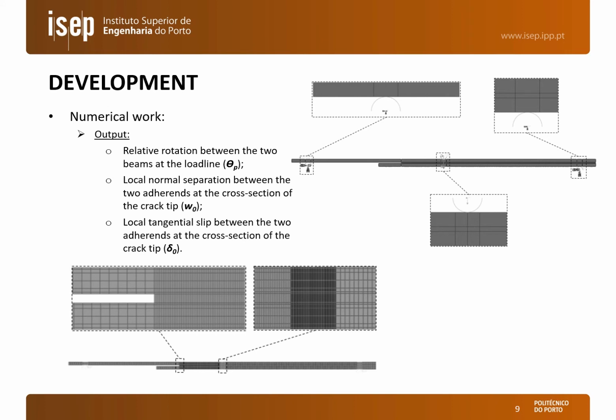Regarding the numerical work, we performed numerical models of the SLB tests such that we could extract 3 relevant parameters to obtain the G1 and G2 and also the cohesive laws in tension and shear, and these 3 parameters are the relative rotation between the 2 beams at the loading line, theta p, the local separation at the crack tip in tension, w0, and the local separation in shear at the crack tip, delta 0.